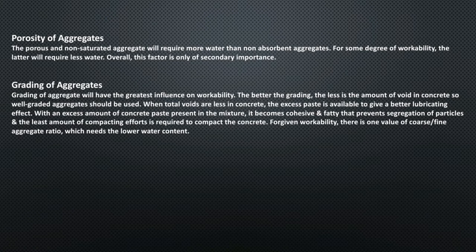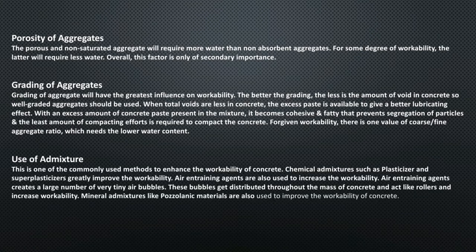Factor number six is grading of aggregates. Grading of aggregate has the greatest influence on workability. The better the grading, the less is the amount of void in concrete, so well-graded aggregates should be used. When total voids are less in concrete, excess paste is available to give a better lubricating effect. With an excess amount of paste present, the mixture becomes cohesive and fatty, which prevents segregation and requires the least compacting effort. For a given workability, there is one value of coarse-to-fine aggregate ratio that requires the lowest water content.